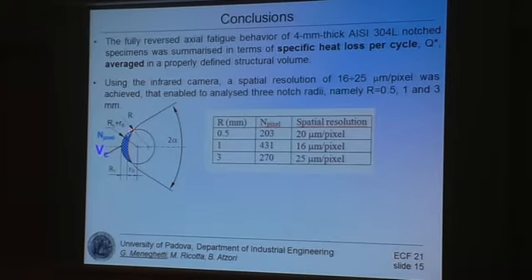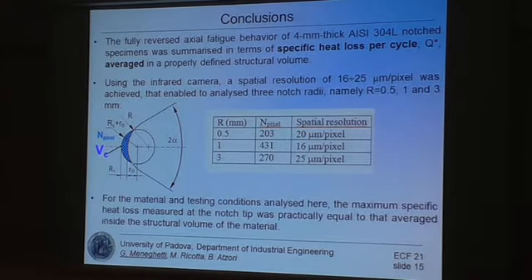Using the infrared camera, a spatial resolution of about 1625 micron per pixel was obtained, and we were able to analyze 3 notch radii, namely 0.5, 1, and 3 millimeters. You see here the concept. We have a number of pixels inside the structural volume where we have averaged the energy dissipated, and you see the spatial resolution that we have obtained in these cases.